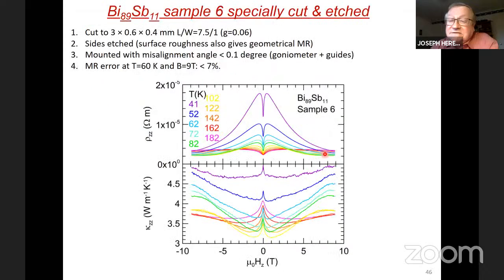So then, after having broken a large number of samples and having highly frustrated the graduate student, Zong, who did these measurements, after 18 months of work, we managed to get one sample cut with a length to width ratio of 7.5:1. And then the samples have to be etched. The sides have to be etched. If you have slight ripples on the sides of the sample, that too gives you a geometrical magneto resistance. It's another story, but it can also create errors. And then the samples were mounted using goniometers and guides, and we have the accuracy of the mounting within less than 0.1 degree, which really is within the error of the goniometer now.